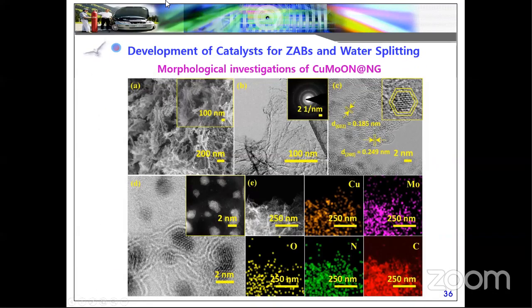So, the development of catalyst towards trifunctional activities. This catalyst was first confirmed by FESEM. You can see the high porosity, and the graphene and metal hybrids, with high porosity and high surface area. And from the TEM analysis, ultrathin particles, because the particle size is very, very small, are homogeneously distributed over the NG nanosheets, nitrogen-doped graphene nanosheets.